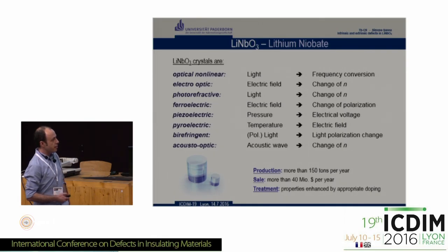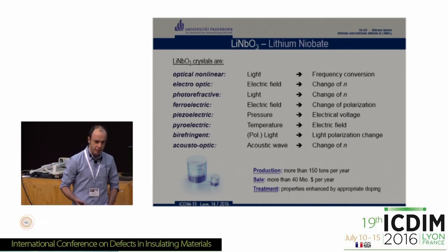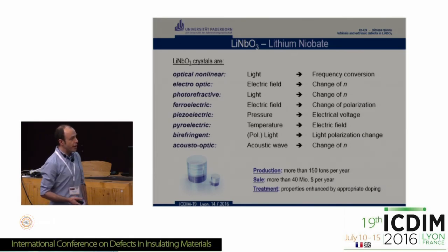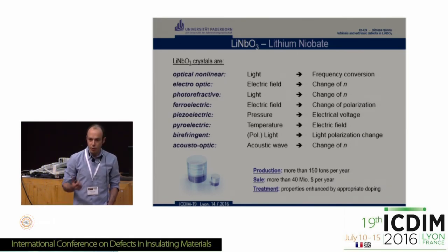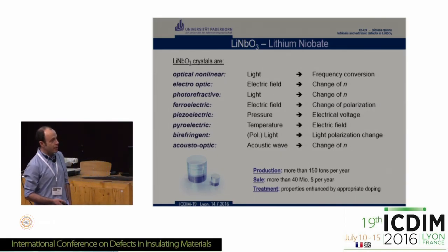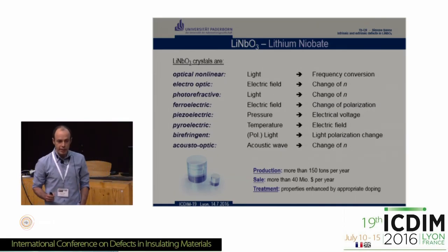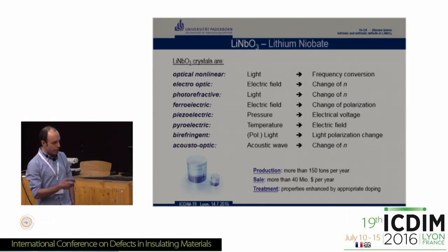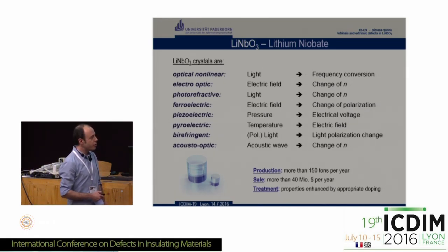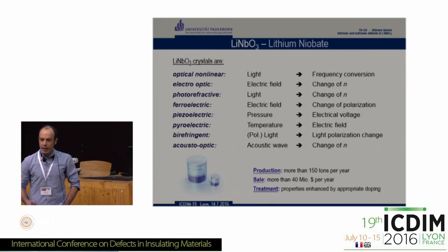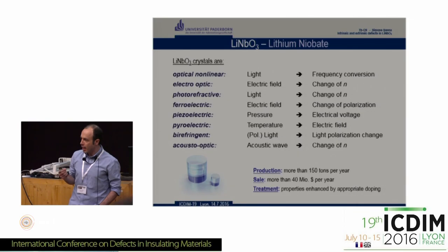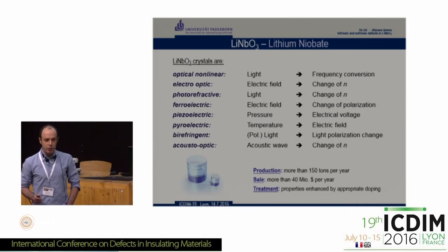Why should one put such an effort into the simulation of lithium niobate? Well, the reason is that there are many, many properties of the material which are exploited for applications. The material is, for example, acousto-optic, which means that you can use it for surface acoustic wave devices. The material is also photorefractive, which means you can use it for holographic data storage. And the material is also optically nonlinear, which means you can use it, for example, for frequency doubling.